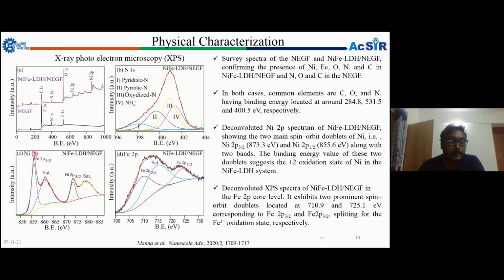Further, in the deconvoluted spectra of nickel 2p, we can see two peaks and two satellite peaks formed. By comparing the binding energy, that suggests the presence of nickel in the plus 2 oxidation state. Another one is the iron 2p, which forms two deconvoluted peaks, suggesting the presence of iron in the plus 3 oxidation state by comparison. So from these we can confirm that the nickel iron layer double hydroxide has nickel plus 2 and iron plus 3 oxidation states. From this kind of physical characterization we confirm the nickel iron layer double hydroxide formation, its uniform distribution, and the importance of nitrogen.